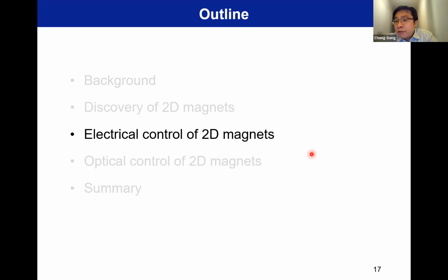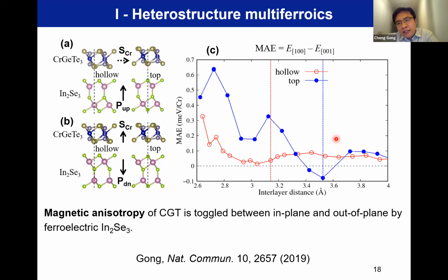The other one is electric field control, but usually the externally applied electric field is very small compared with the inherent crystal field. And if you want to apply a larger field, probably you will break up the substrate or some materials in this device stack. So usually the applied electric field is maybe 1,000 times smaller than the inherent crystal field. It's very hard to change the crystal field by external field. So you can see both ways are not easy. But you sense already, if we can change the electric field, the crystal field, that's very good.